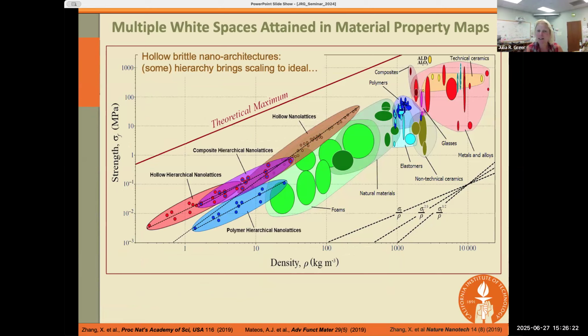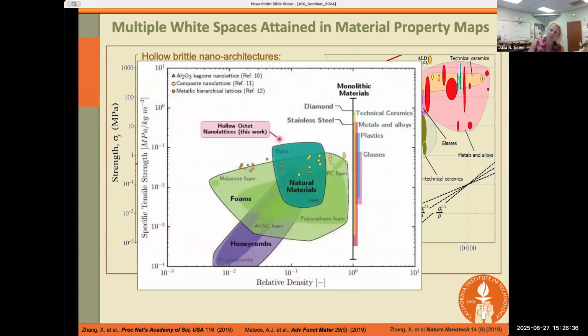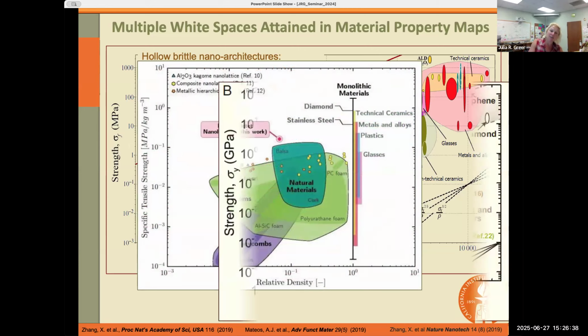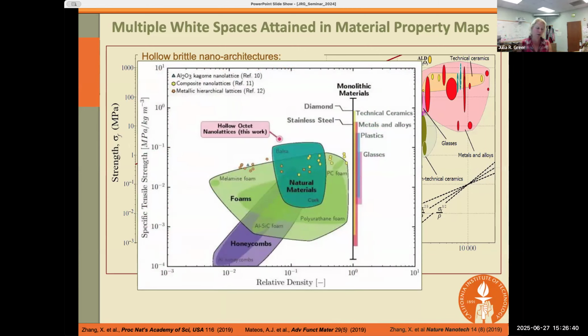But you can see right away that, for example, the hierarchical nanolattices were able to buy us 2 extra orders of magnitude reduction in relative density. So there's plenty of potential, and certainly we and maybe many other groups can get much farther into the white space now. We learned that in tension, the specific tensile strength of these alumina nanolattices supersedes that of, say, balsa wood, which is a material you would use for kayaks or for any kind of lightweight sports equipment. So there's a lot of promise in that.